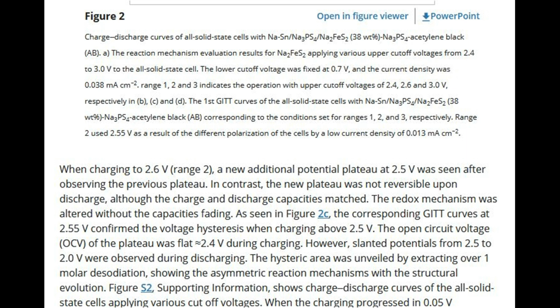As seen in Figure 2c, the corresponding GITT curves at 2.55 V confirmed the voltage hysteresis when charging above 2.5 V. The open circuit voltage, OCV, of the plateau was flat at 2.4 V during charging. However, slanted potentials from 2.5 to 2.0 V were observed during discharging. The hysteretic area was unveiled by extracting over 1 molar desodiation, showing the asymmetric reaction mechanisms with the structural evolution. Figure S2, supporting information, shows charge-discharge curves of the all-solid-state cells applying various cutoff voltages.